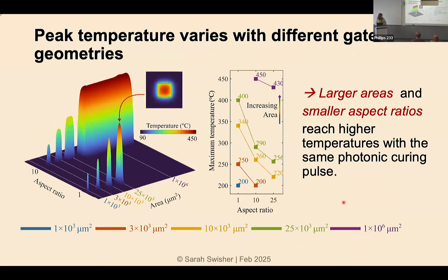When we run this simulation, we see a huge variation in the peak temperature, that curing temperature, with different gate geometries. So this is looking at the thermal map of gates that would have a different aspect ratio and a different area. So we looked at area, aspect ratio, and we also looked at shape. Does a rectangle behave differently than an ellipse? And the key point that I want you to see here is that, again, the same photonic curing pulse is applied to all of these devices.